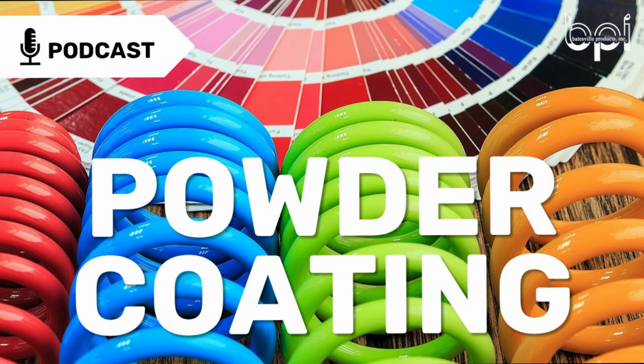The quick way is to take either MEK, which you can buy at Lowe's, it's methyl ethyl ketone, or acetone, which is basically fingernail polish remover, and you saturate a rag, put it on the part, and take about a 3-inch swipe back and forth. That's called one double rub. Do that 25 times in the same spot, and if you do not go through the substrate, you have a good part.